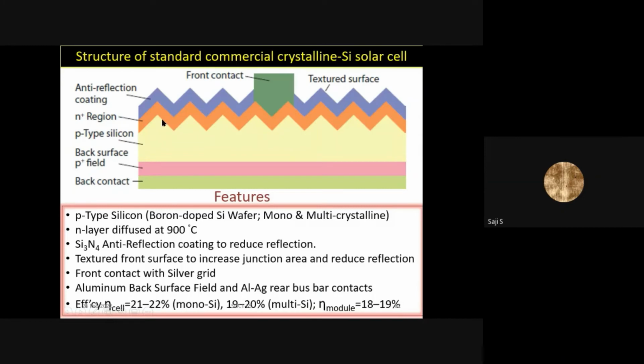Now, the crystalline solar cell, we will just briefly describe its structure. It has a p-type silicon base layer, which is a boron-doped silicon wafer. It can be either a mono or multicrystalline wafer, on which an n-type region is formed. That is, the phosphorus layer is diffused at about 900 degrees centigrade, and over it an anti-reflection coating layer is deposited, which is a silicon nitride coating. The silicon nitride coating is to reduce the reflection on the surface of this silicon solar cell. And finally, the contacts are deposited. A fine silver contact is deposited. And the efficiencies are, of course, as I said, 21% for mono cell and about 19-20% for multi cell.